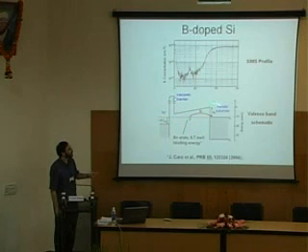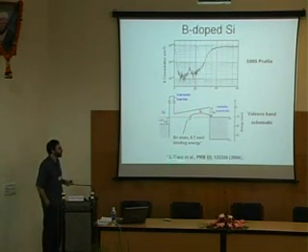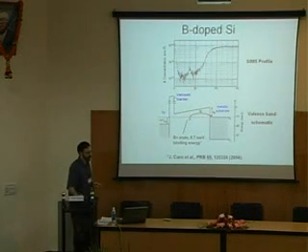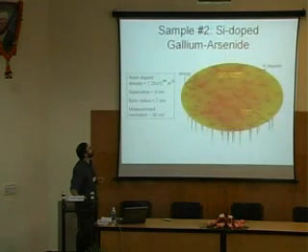And fortunately, also, this sample is very well characterized by Sven Roge's group in the Netherlands. We know that we have one state that's empty. It's called the E+ state, and it's about 6 millielectronvolts below the top of the valence band. So we know about what energy the electron is supposed to be at. Here is a SIMS profile of the sample. That was sample number 1.